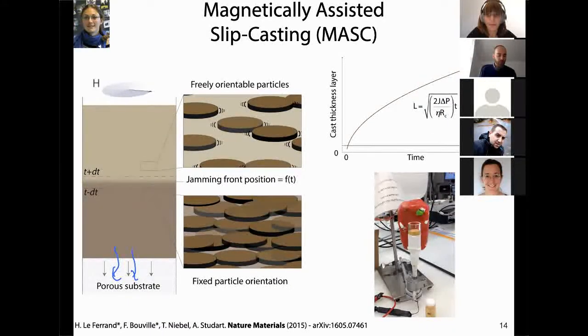Of course, because this is time dependent, as you remove more and more water, the jamming front position, the separation between the position where the particles are jammed and where they are free, is moving over time. We know the description: it goes as the square root of time, so we can predict where this cake layer thickness is going to be as a function of time. That allows us to do some process control.